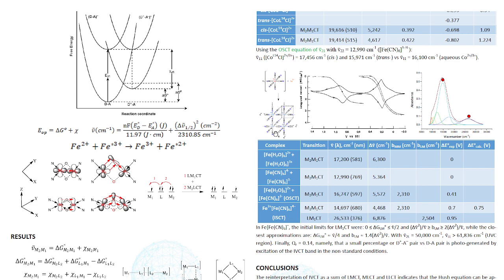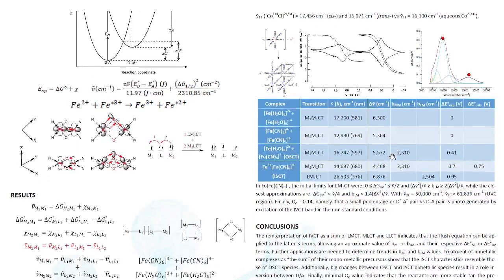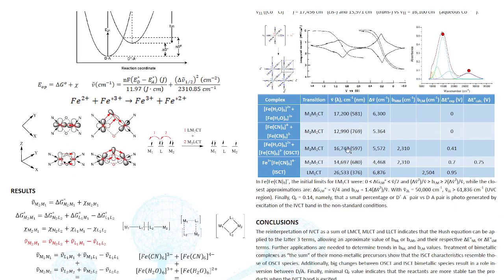The iron with the carbon attached to it becomes the donor species, whereas the iron that is coordinated to the nitrogen, the one from the iron chloride, becomes the acceptor. We have the cyclic voltammograms of the Prussian blue and its absorption spectra deconstructed in Gaussian shapes. And in this case, we have the same relationship, where the monometallic precursors are related to the bimetallic cases. One is the outer sphere dimer, and the other is an inner sphere, the bimetallic complex as such.